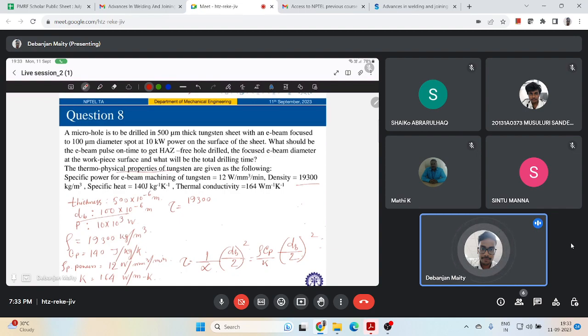19,300. This is in kg per meter cube, which is rho. Cp value is 140 joule per kg Kelvin. This is Cp. K is 164 watt per meter Kelvin. This is conductivity, and that into my dB is 100 into 10 to the minus 6, that divided by 2. So 50 into 10 to the minus 6, that whole square. How much is this coming? Just 19,300 into 140 into 50 into 10 to the minus 6, that whole square, divided by 164 equal to. So this is for me coming as 4.12 into 10 to the minus 5 second.